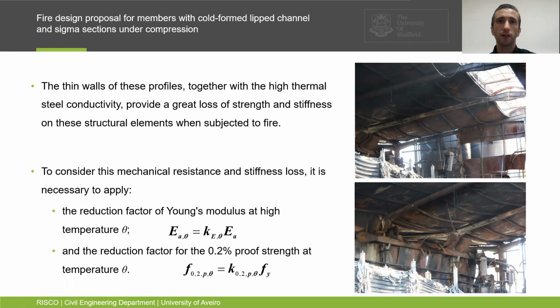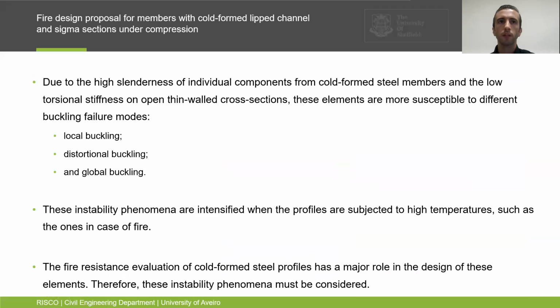Since steel has a high thermal conductivity, when subjected to high temperatures, mechanical properties start to deteriorate from a certain moment, leading to a loss of strength and stiffness, which means that we have to consider the reduction factors of the Young's modulus and proportional limit strength. These profiles present specific characteristics which lead to local, distortional, and global buckling phenomena. At elevated temperature, these instability phenomena are intensified, which means that they should be considered in the fire resistance evaluation.